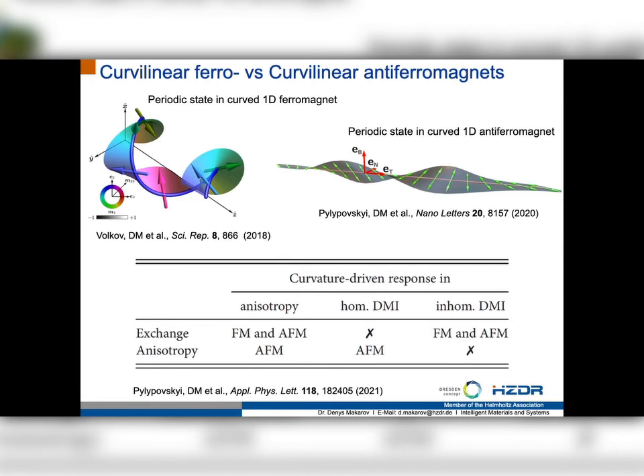For example, if you want to have a homogeneous Dzyaloshinskii-Moriya interaction, you will need to get it from anisotropy in a curvilinear antiferromagnet, and this cannot be obtained in ferromagnets at all. From exchange, this term does not appear. At the same time, if you have an inhomogeneous DMI, the intrinsic Dzyaloshinskii-Moriya interaction, you can get this from exchange interaction both in ferromagnets and antiferromagnets, but not from anisotropy and things like this. So basically, by analyzing this table, you can really see the differences which you can have in curvilinear ferro- and